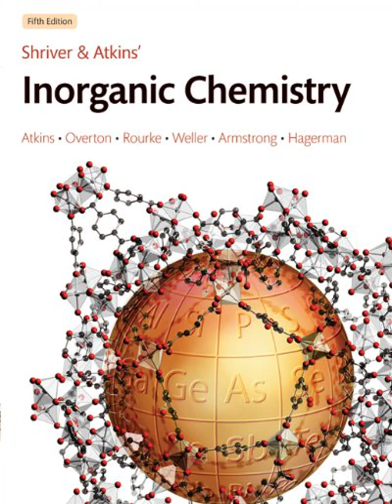Whoa. What causes that, and what could we use it for? It's linked to a mechanism called double exchange between Mn ions. Applying a field aligns the manganese spins, allowing electrons to hop much more easily between them, switching the material from insulating to conducting. The potential is huge for magnetic data storage, think read heads for hard drives, and potentially for future spintronics, using electron spin instead of charge for information processing.